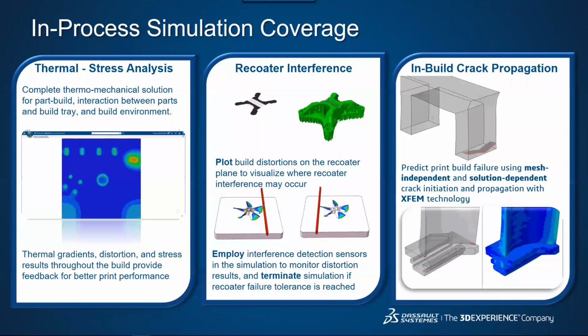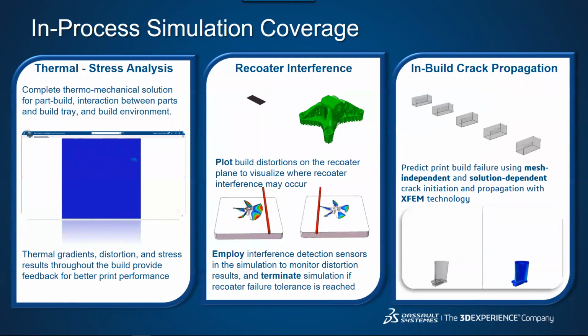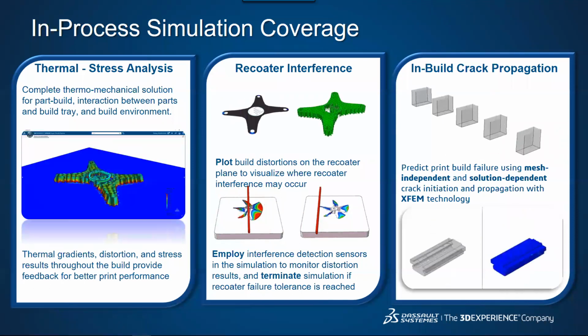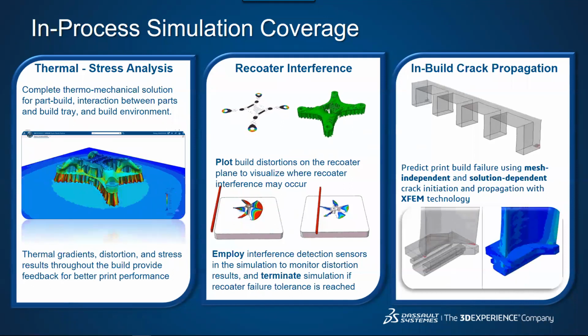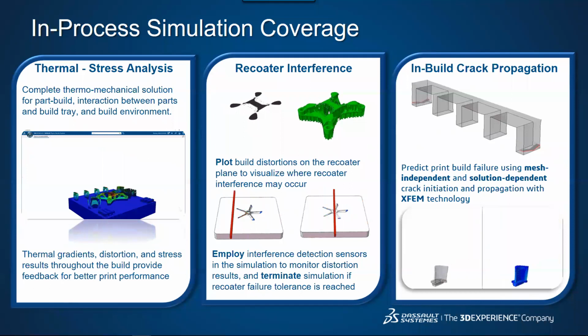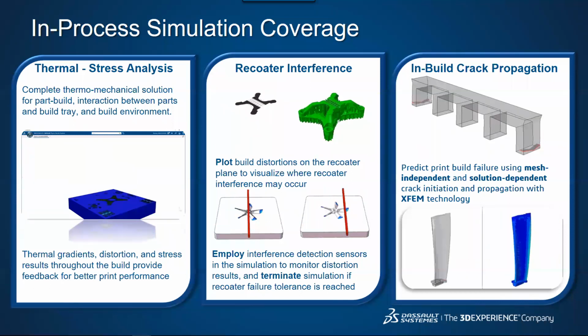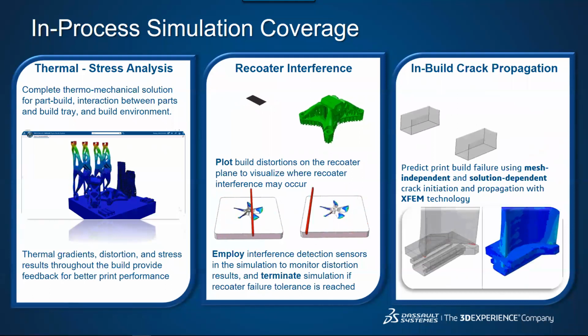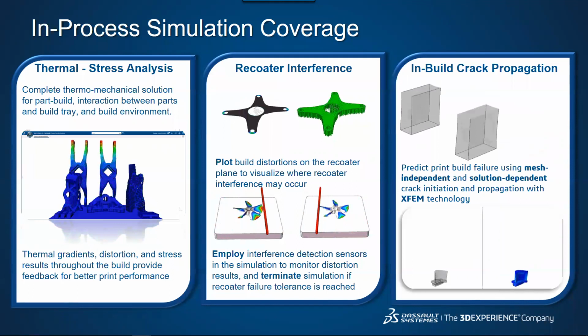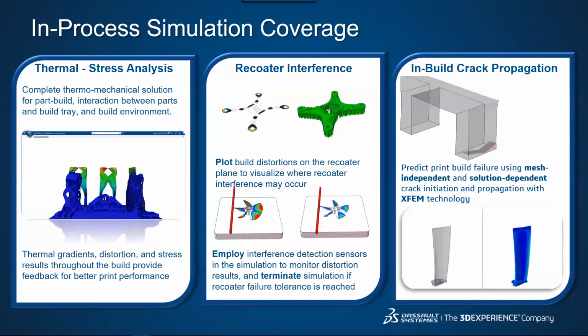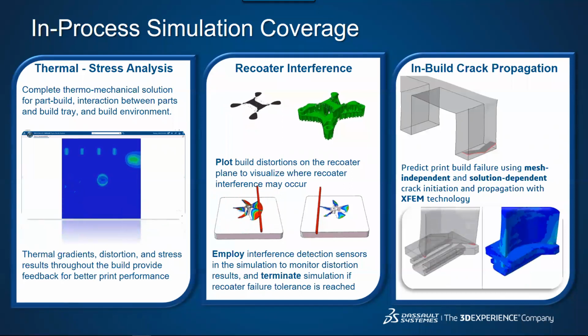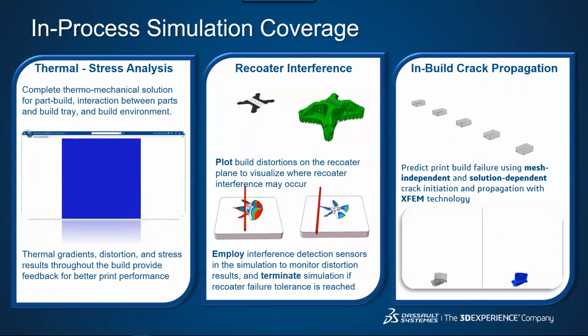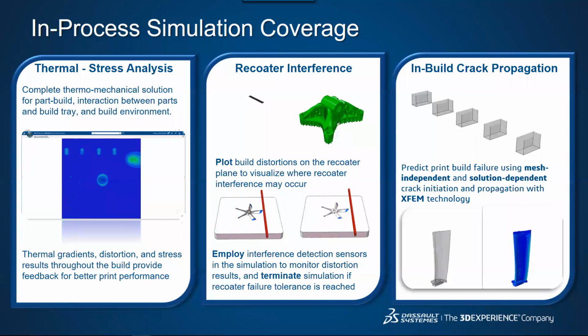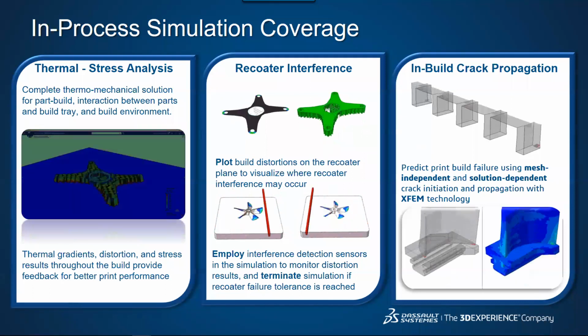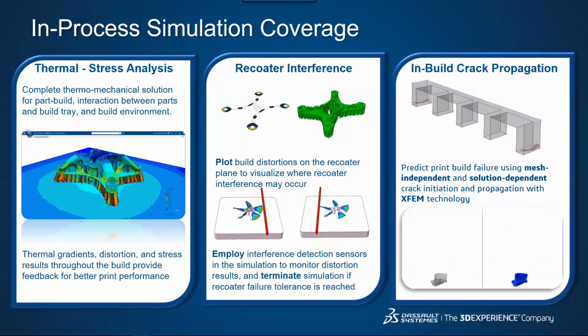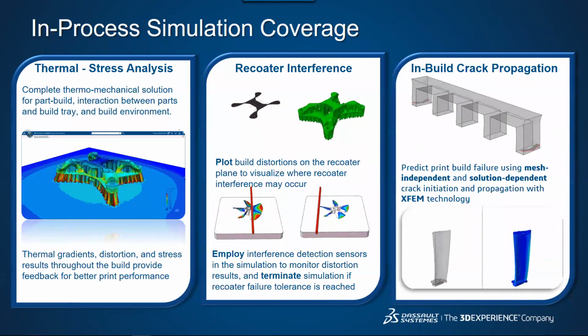Another reason that build failure occurs is due to high stresses that occur during the build, which may lead to crack initiation and propagation. Because our process simulation tools are built upon our comprehensive Abaqus nonlinear FEM solver, we can also predict mesh-independent crack initiation and growth, based on a given failure criterion, by using existing XFEM technology. So we can put an XFEM enriched region in a build model to look for crack initiation or growth during that build. So we can see that these process simulation technologies can be used to predict different mechanisms of build failure, so that you can virtually optimize your successful build before you begin doing build iterations.